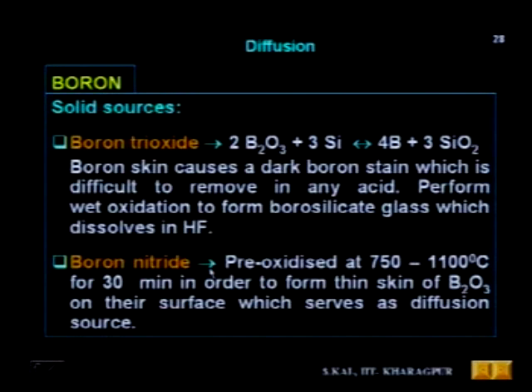Now here also boron nitride is first activated. Pre-oxidized means this process is known as activation of boron nitride. In the presence of oxygen, if you heat the boron nitride for a long time, then a thin layer of B2O3 will be formed at the boron nitride surface. Now this boron nitride cake is kept in close vicinity of the silicon wafer in the furnace, at a high temperature ranging from 900 to 1100 degrees centigrade. So the B2O3, boron trioxide, with silicon will form boron and silicon dioxide. The same reaction will follow, and this boron will diffuse into silicon.